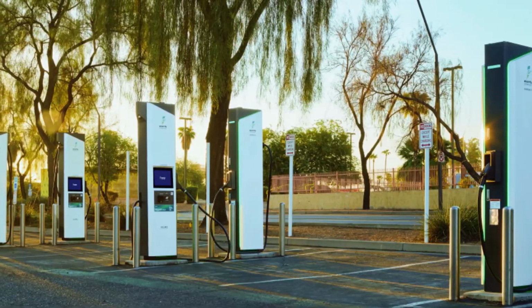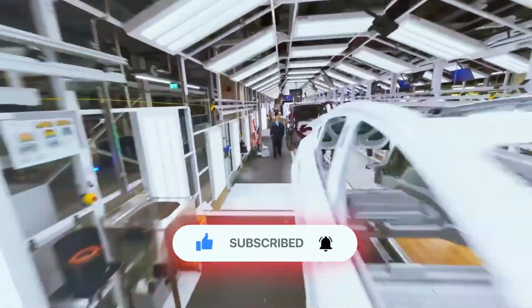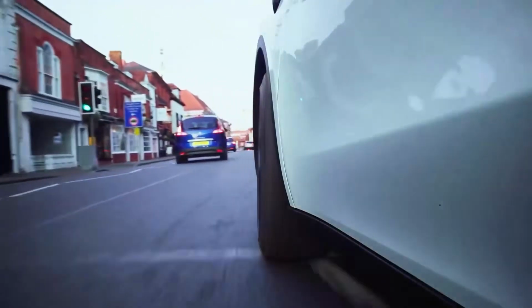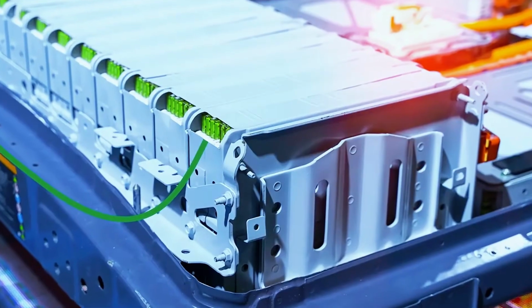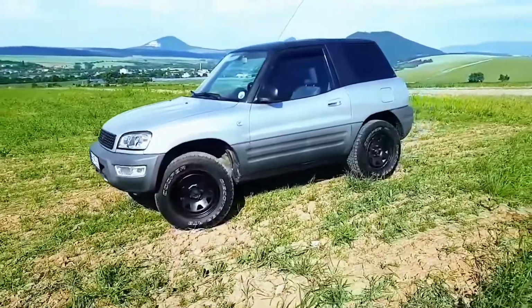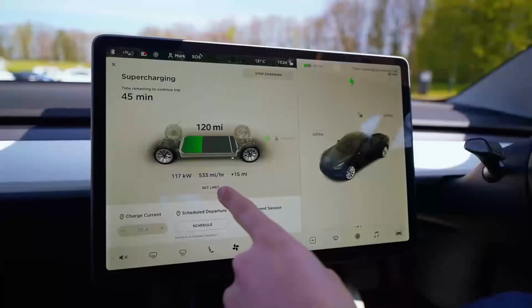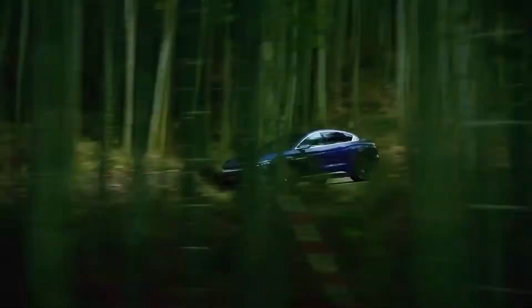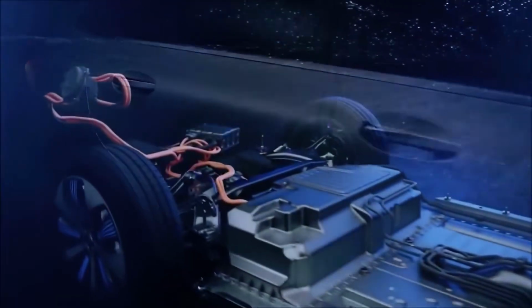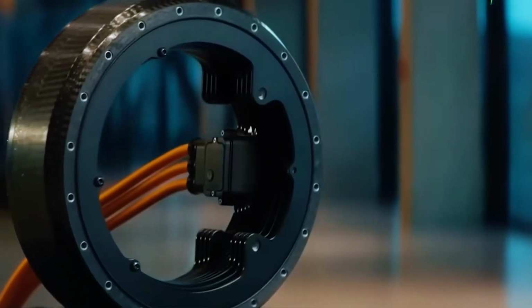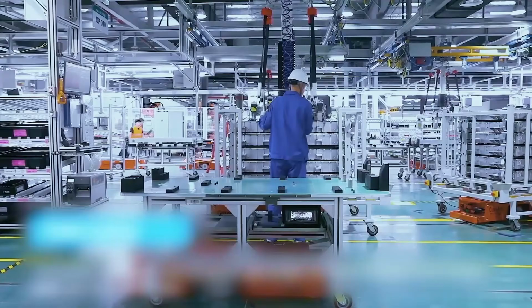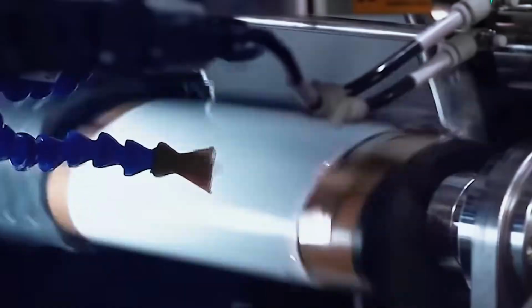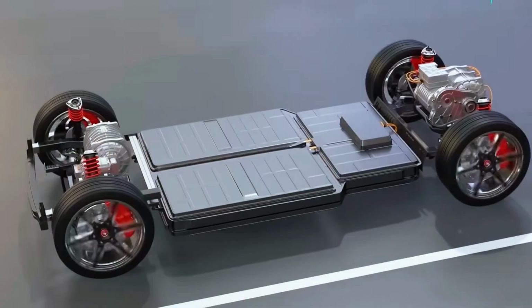The best lithium-ion cells available today, including the ones inside a Tesla Model Y, a BYD Seal, and a Hyundai Ioniq 6, achieve somewhere between 250 and 300 watt-hours per kilogram at the cell level. Already impressive. But at the pack level, once you account for the thermal management hardware, the structural components, the cooling channels, the wiring, the containment systems, that number drops. Sometimes to as low as 160 watt-hours per kilogram. That gap is not an engineering failure. It is the inherent cost of safely managing a liquid electrolyte at scale. You pay for the liquid's instability in mass, volume, and complexity.